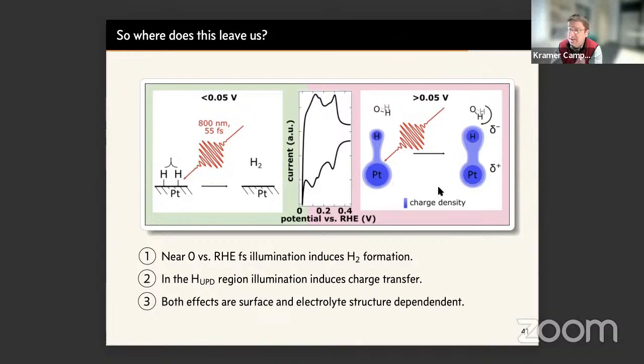So even in that experiment, there is this mismatch in timescales that you describe, so that the thermalization happens on about 5 or 10 picosecond timescales for direct resonant excitation in solution. All the stuff that happens faster than this sees the unperturbed structure. But again, the experiments that I showed you here use laser photon energies which are very weakly absorbed by the solvent, so the direct heating effect on the solvent is very weak.